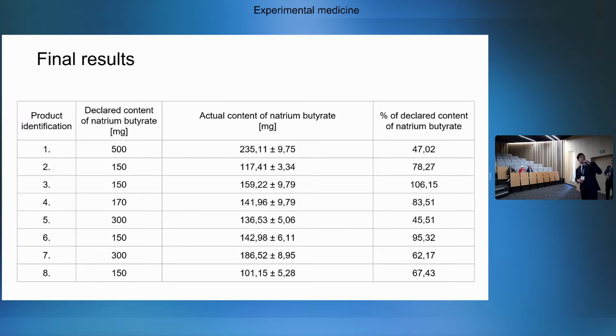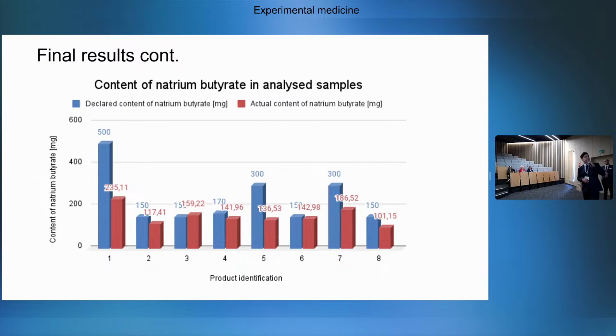Here we present you our final results. As you can see, all of these substances contained natrium butyrate, and the percentage of declared content varied from 40 to more than 100% of declared content. We also summarize that in this chart. As you can see, 5 out of 8 had really similar content to the declared content by the producers.